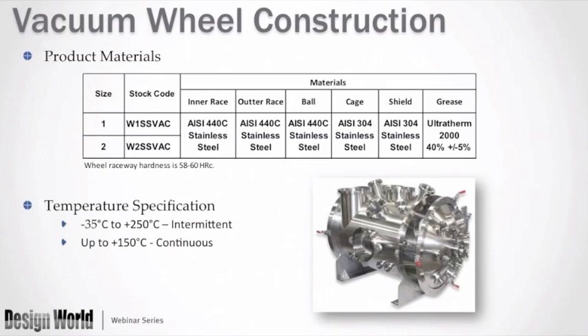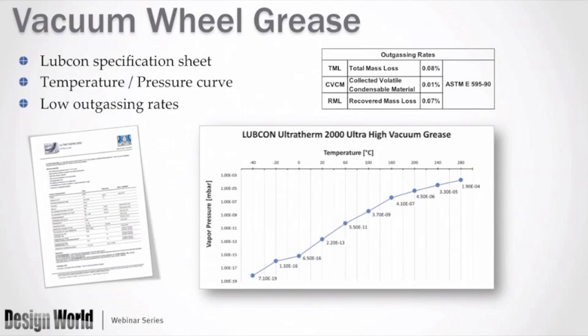If you can see here some of the materials that we use in there, it's all stainless construction and grease. The grease is capable of withstanding temperature. In most cases on a bearing, the grease is a limiting factor for the temperature ranges, usually not the materials. In some cases you will get to an elevated temperature and melt the rubber, the NBR seal. But in this case the grease can handle up to 250 degrees C intermittently, or up to 150 degrees C continuously in a vacuum chamber environment. The grease itself, of course, has a curve of temperature versus vapor pressure, and it's very low outgassing as well.